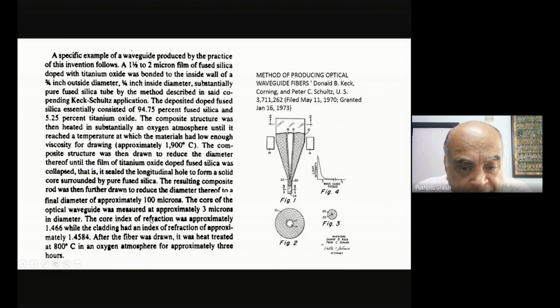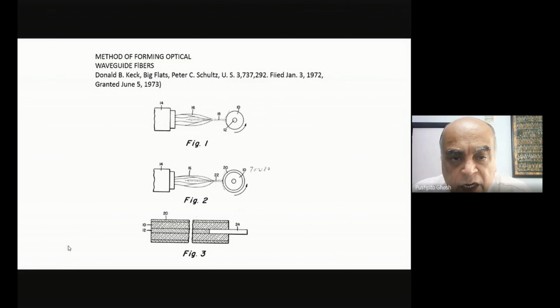The core index of refraction was approximately 1.466, while the cladding had an index of refraction of approximately 1.4584. So you can see how tiny the difference is. If you were to look at the first decimal place, you would not see any difference between the two. After the fiber was drawn, it was heat treated at 800 degrees centigrade in an oxygen atmosphere for approximately 3 hours. Now the question is how exactly they're saying that you dope it with this. But let us try and see what exactly they are doing.